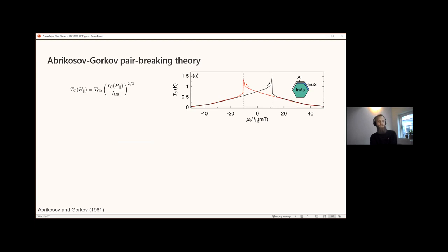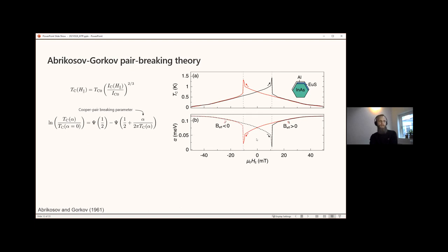We see that around zero applied magnetic field, the critical temperature is around 0.8 Kelvin, confirmed by the previous measurements. And around the coercive field, so plus minus 10 millitesla depending on the sweep direction, the critical temperature spikes to 1.4 to 1.5 Kelvin. We can now take this critical temperature data and extract the Cooper pair breaking parameter alpha using Abrikosov-Gorkov pair breaking theory and the following relation from that. This relation seems tedious as it has a logarithm of reduced temperature and digamma functions on the other side, but it can be solved numerically for a given alpha, and that's what we did. Basically, this gives you alpha and then the energy scale of the Cooper pair breaking parameter corresponding to it.